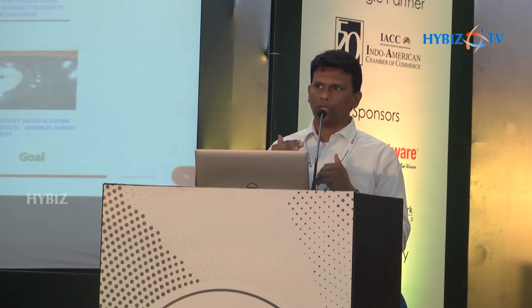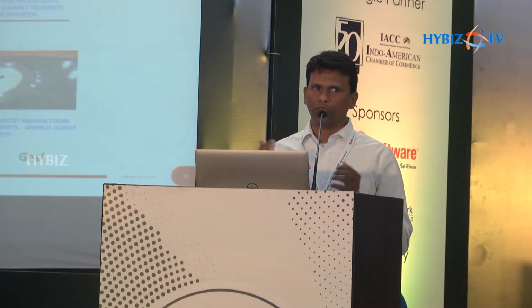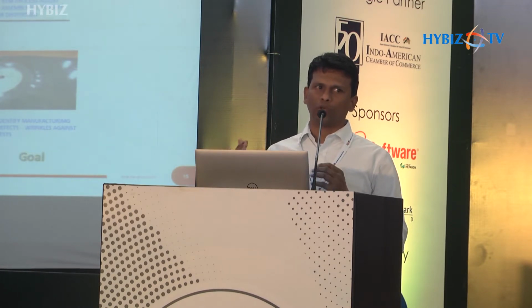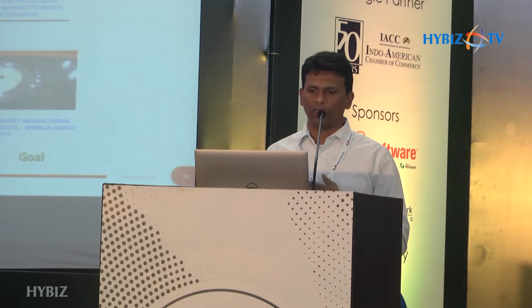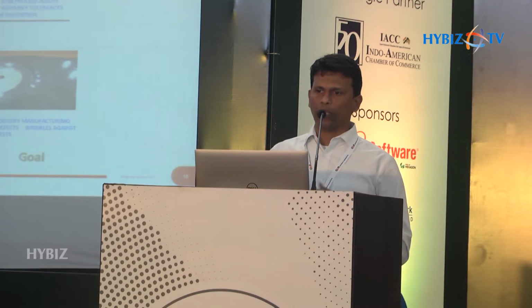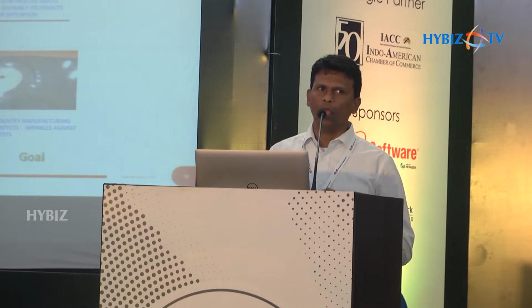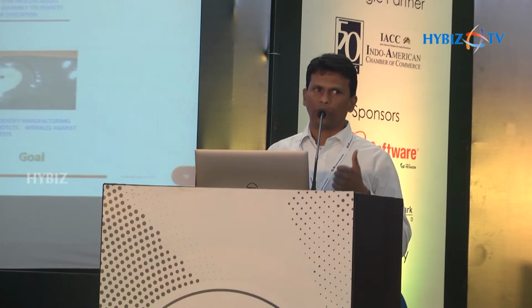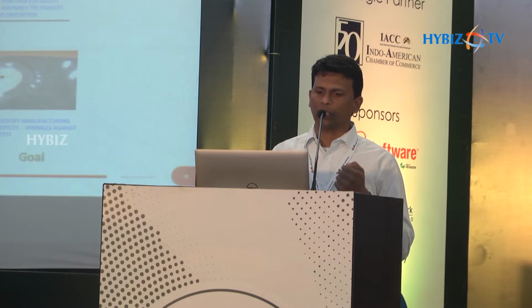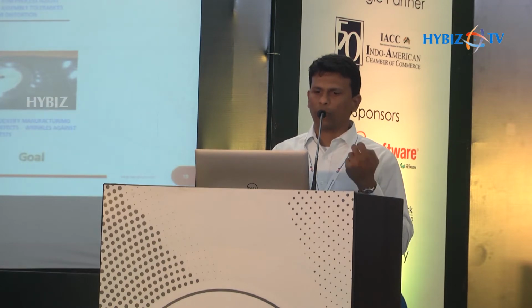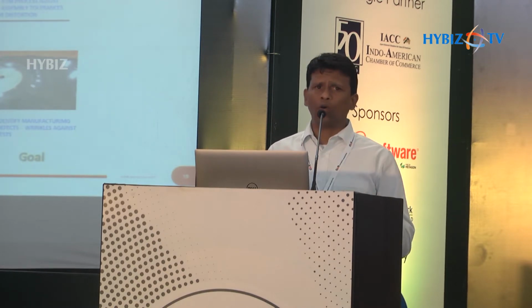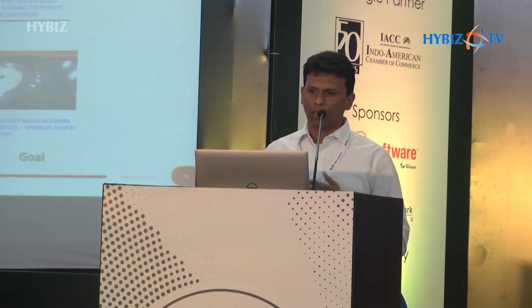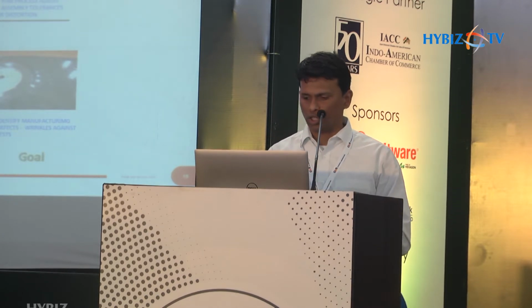When they understood that the amount of distortion was outside the tolerance limit, they went back into the preform. They changed the mold of the preform and basically adapted the preform so that finally, after the distortion, the component was within the tolerance range. So the whole of this simulated process chain was possible because we are able to do the entire chaining process itself, like preforming, the RTM process, and then the distortion associated, along with the compensation, or the preforming compensation, that could be done along with that.